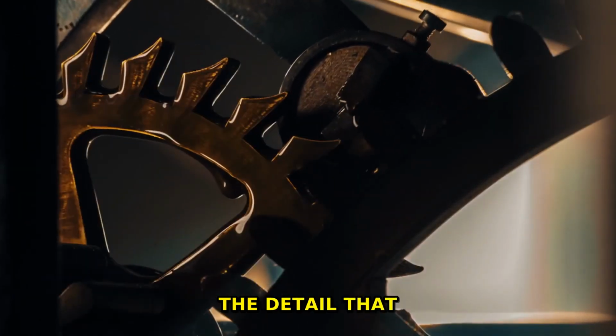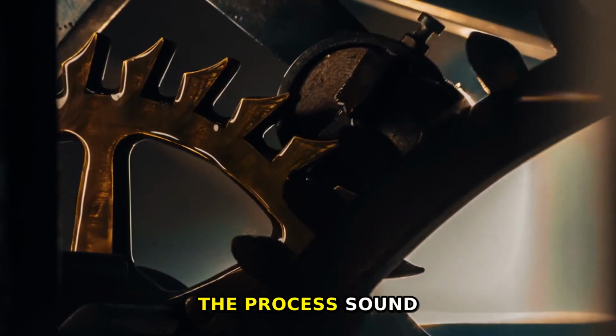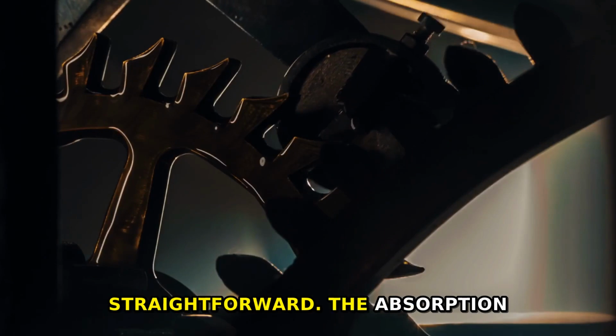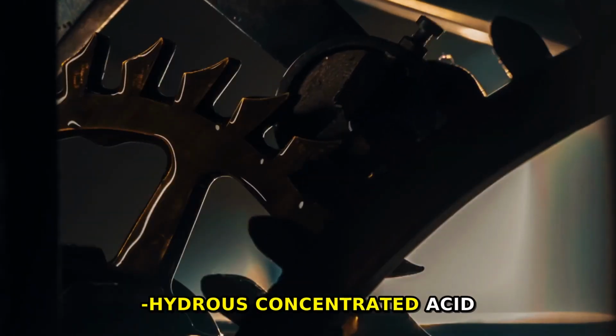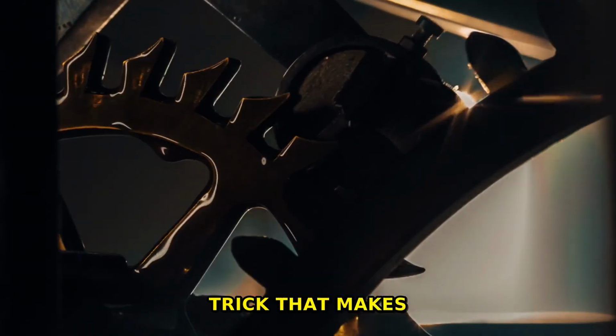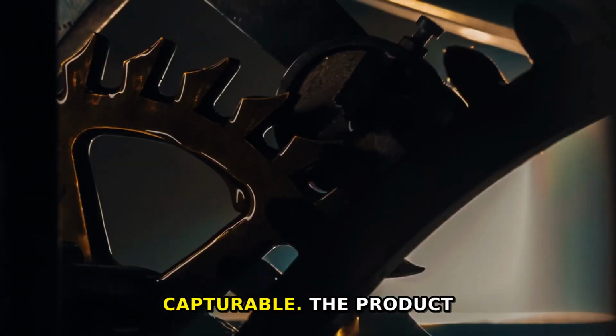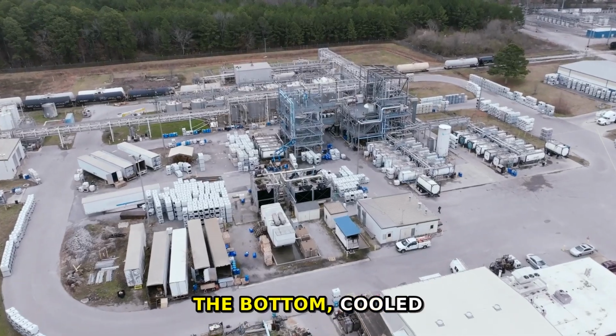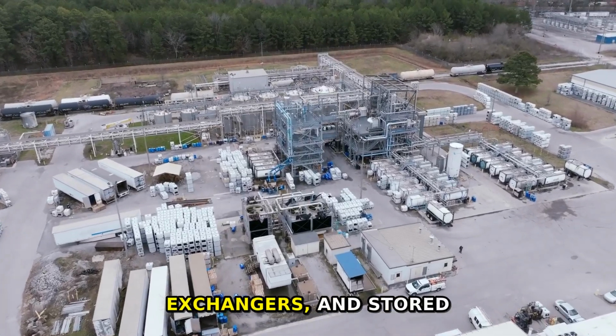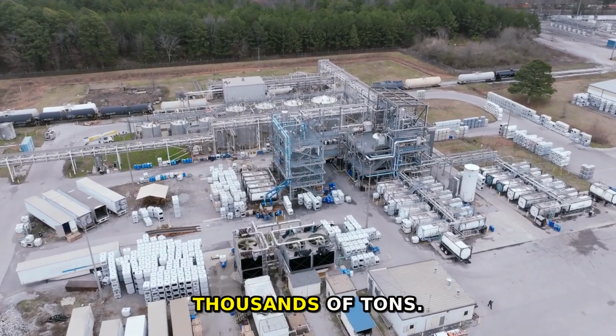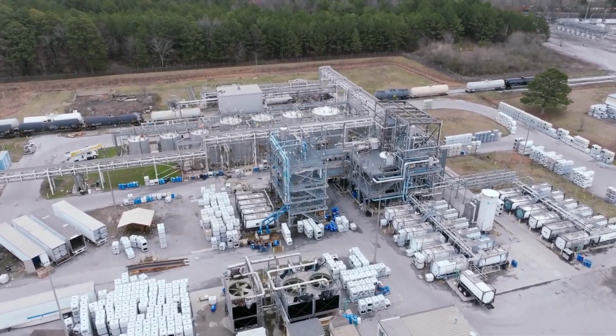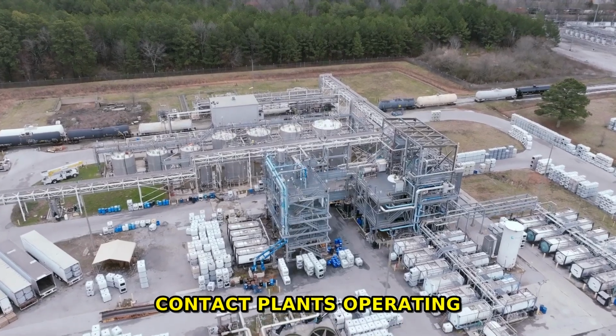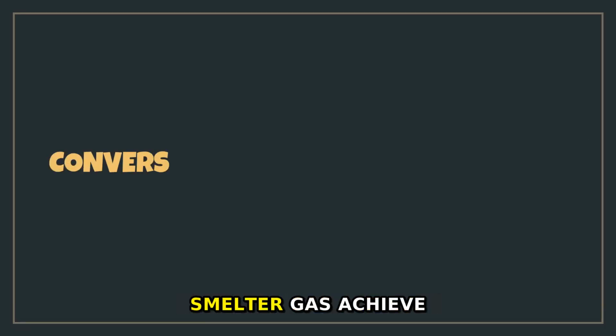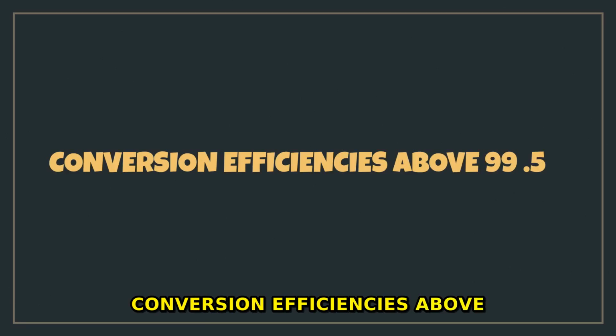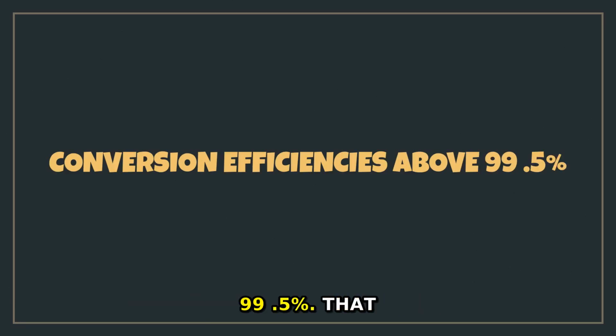This is the detail that trips up most people who think the process sounds straightforward. The absorption into near anhydrous concentrated acid is the precise trick that makes the gas fully capturable. The product is drained from the bottom, cooled in titanium heat exchangers, and stored in tanks holding thousands of tons. Modern double-absorption contact plants operating on high-concentration smelter gas achieve conversion efficiencies above 99.5%.